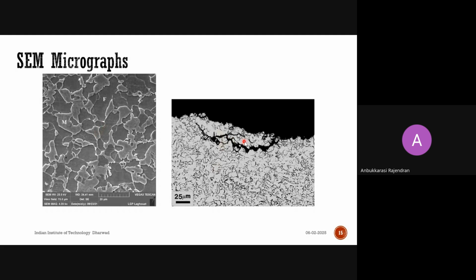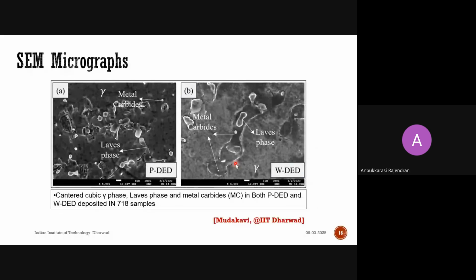If I want to see the crack propagation, whether it is along the grain boundary or through the grain, I must do the etching process on the cracked sample. And if features like precipitates are present, where they are located, whether along the grain boundary or within the phase, all these details I can get if I do the etching process. Okay, so these are some precipitates in the sample. This is one of the nickel samples, which has gamma phase and carbide phases. If I am just looking at the precipitates, I need not go for etching. As I mentioned again, if I want to see the location, I need the etching process.